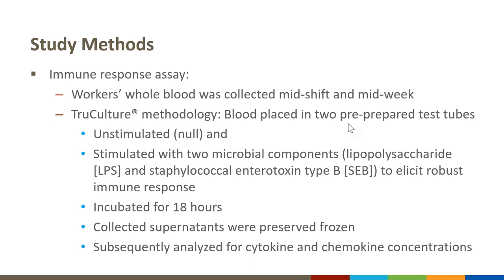The tubes were then incubated for a mean of 18 hours, and it was pretty much right on 18 hours for each participant. And the supernatants were then collected and preserved frozen until all were subsequently analyzed together after the study was finished for the cytokine and chemokine concentrations in both the stimulated and unstimulated tubes.